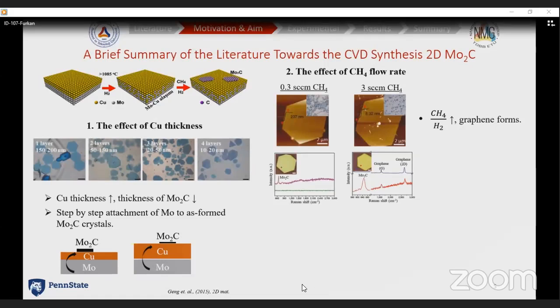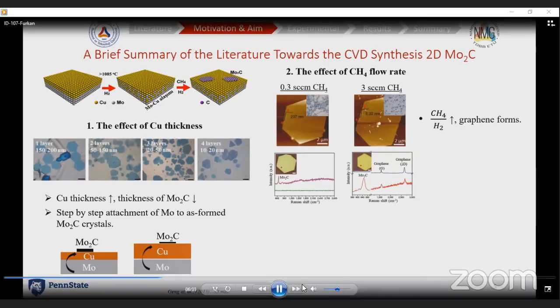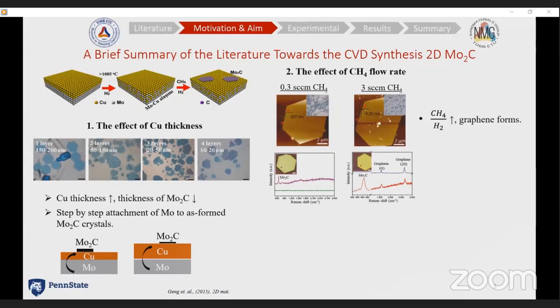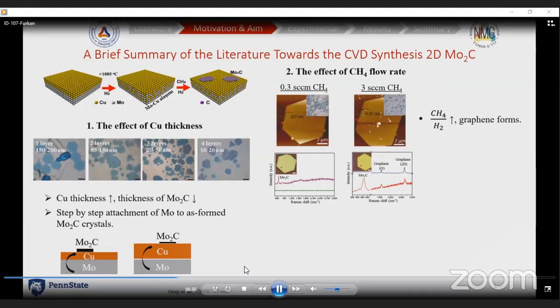And they observed that low methane flow ends up with thicker crystals, while higher methane flow leads to the formation of much thinner molybdenum carbide crystals. And this is because of the graphene formation along with molybdenum carbide on the upper surface for the high flow rate of methane gas. And since this graphene will act as a barrier for the molybdenum diffusion, again, step-by-step attachment of molybdenum species to the as-formed molybdenum carbide crystal leads to thinner crystals.